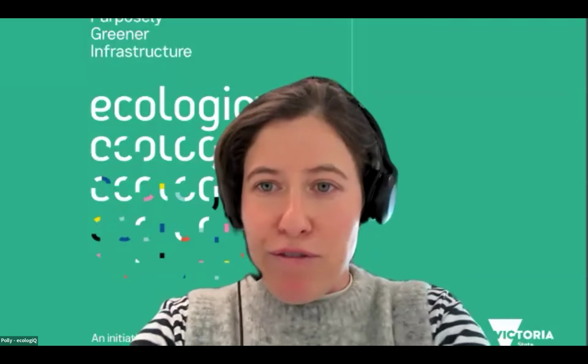No, there are 2 more questions related to durability, and I will say that yes, there is lots of additional durability work being done by Deakin University, and Raquel at Melbourne Uni. There is one specific question here on creep. Raquel has been doing some long-term creep testing, and the results are very, very surprising. Part of that excitement is long-term creep performance and durability, with the possibility of getting this mix, because these clays are so reactive, to get materials that have very low permeability, and therefore durability is going to be way improved because of the permeability performance. Thanks, Estella.